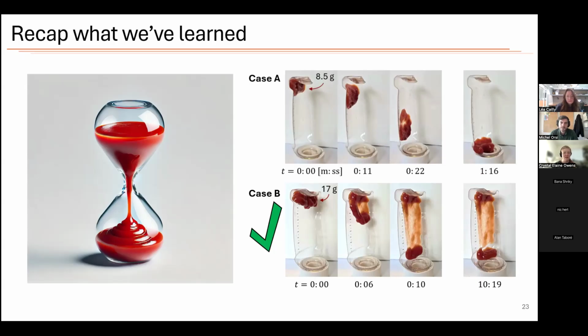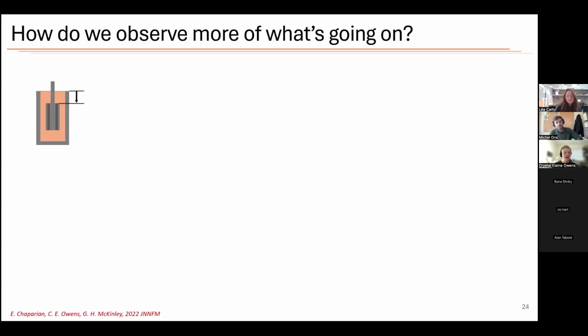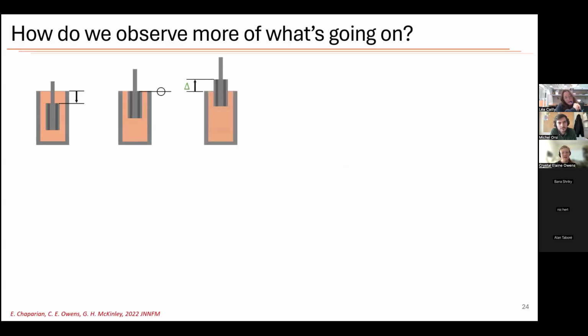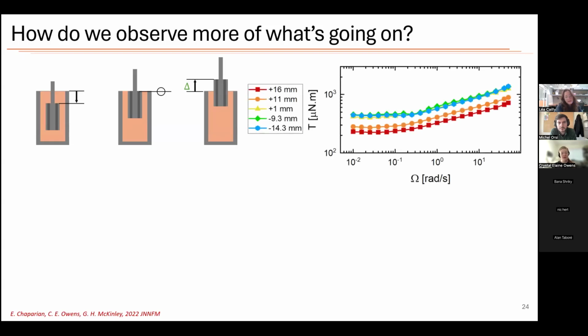But the first case, where the material slides down the sidewalls, is something we haven't discussed at all, because one of the reasons we use vanes for measurement is avoiding slip entirely. But we will now want to understand slip, so we have to do something a little bit different. So to do this, we went back to the lab, and the normal rule of using a vane is you want to insert it completely into the material. But we decided to break the rules of measurement and actually measure with the vane at different heights, either at the surface or a little bit above. And we measured the same flow curve we had before.